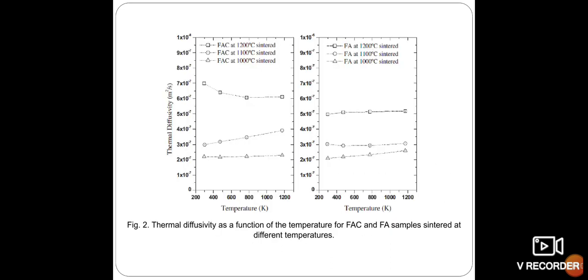From these graphs, it depends on the densification degrees of the specimens. The thermal diffusivity values of FAC and FA denser specimens that are sintered at 1200 degrees centigrade turn out to be higher for the whole temperature range in comparison with the diffusivity of the samples sintered at lower temperatures, that is 1000 and 1100 degrees centigrade.